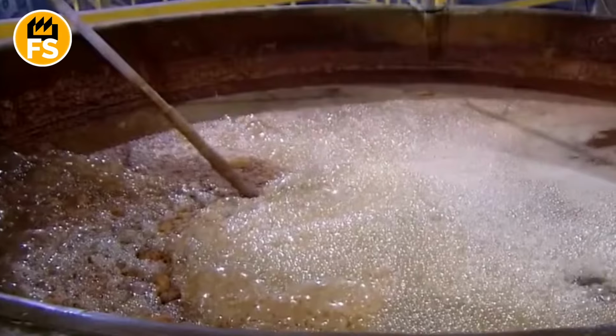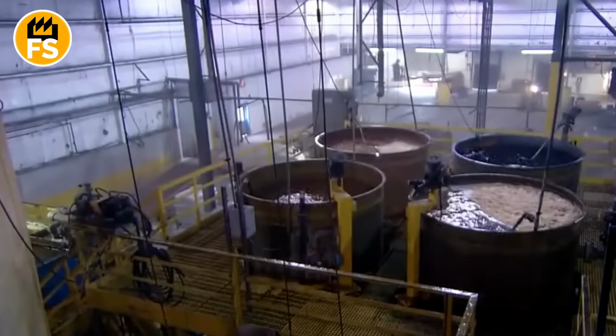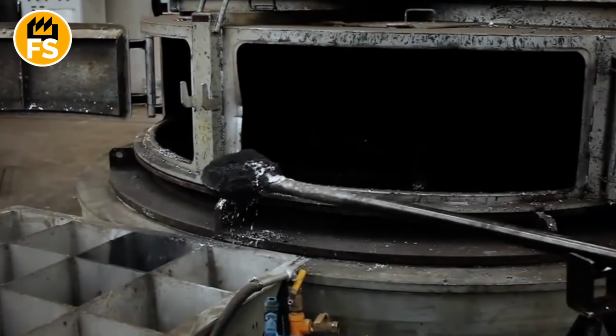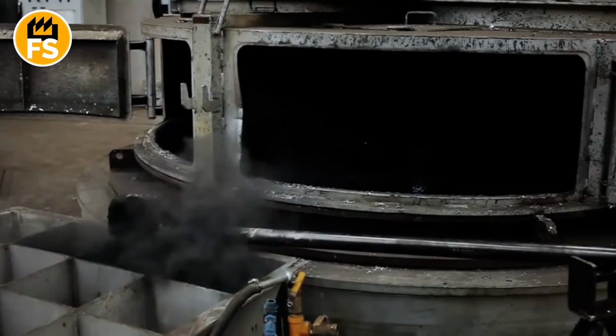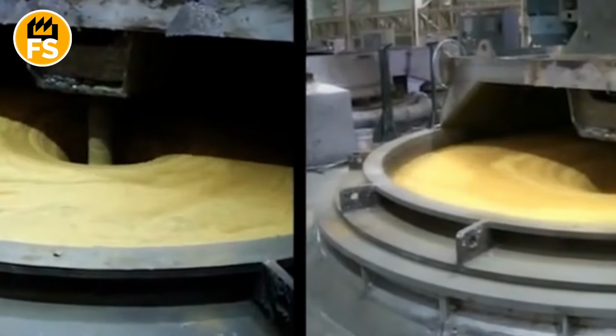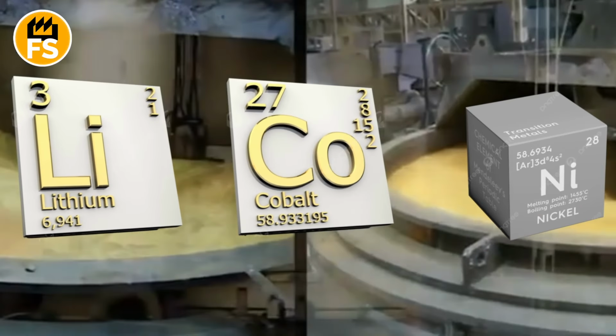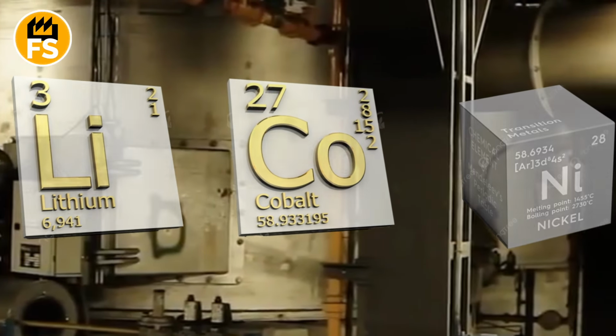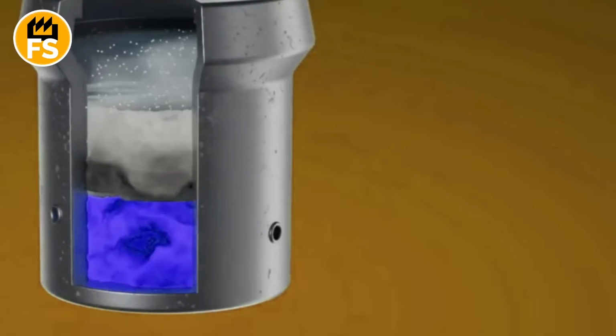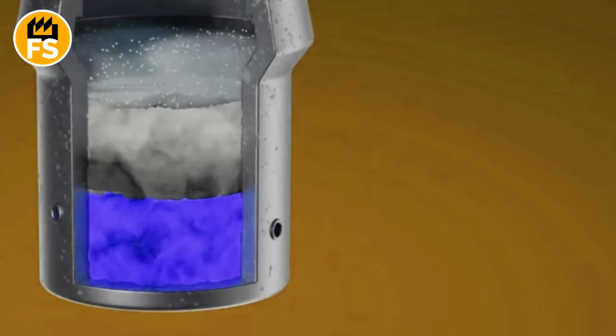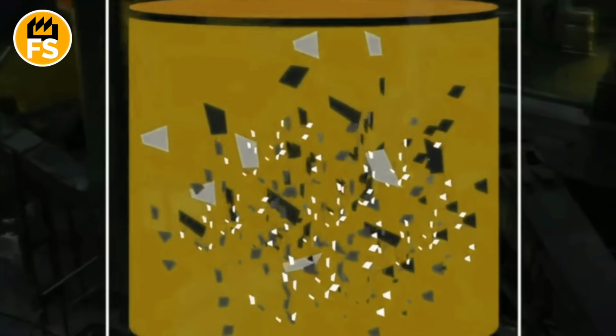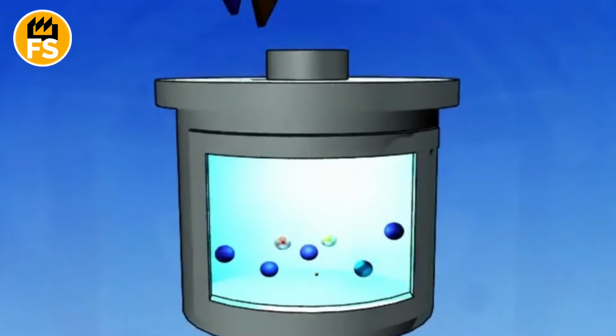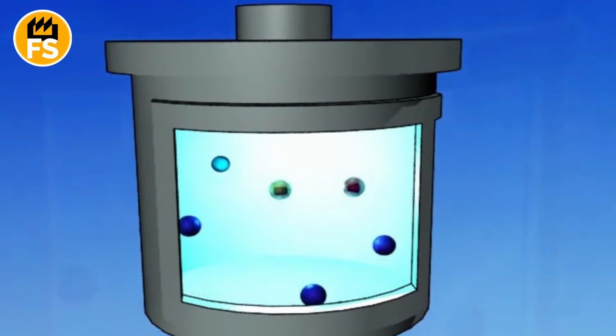Battery fragments are immersed in special acid solutions. There are huge tanks where a yellowish-green liquid is bubbling. This could be sulfuric or hydrochloric acid. During immersion, a reaction occurs. Lithium, cobalt, nickel, and other metals literally dissolve in this soup. To extract the desired metal, a clever trick is used: ion extraction. Special reagents, for example, organic compounds, are added to the liquid, which capture a specific metal, like a magnet. As a result, each metal settles into a separate layer.